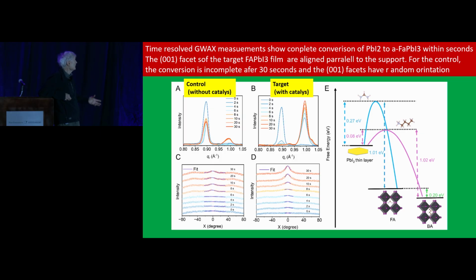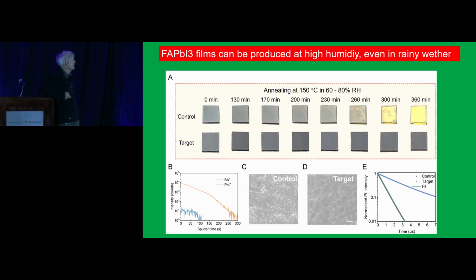If you use bulk PbI2, it doesn't work well. It doesn't convert well to the desired formamidinium perovskite. And here's another very interesting feature. You can form these black films, the lead iodide films, even in rainwater. Usually they're very humidity sensitive. And so how is that? Well, we have the butylammonium cations on the surface. They're hydrophobic, and they reject the water ingression into these films.